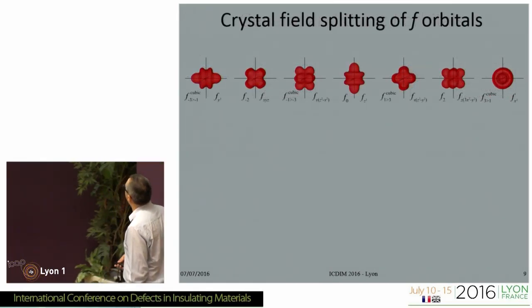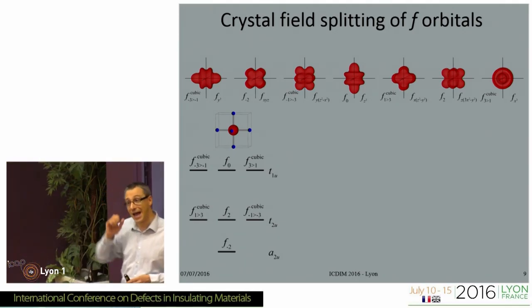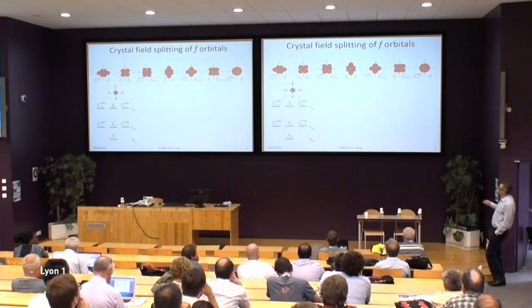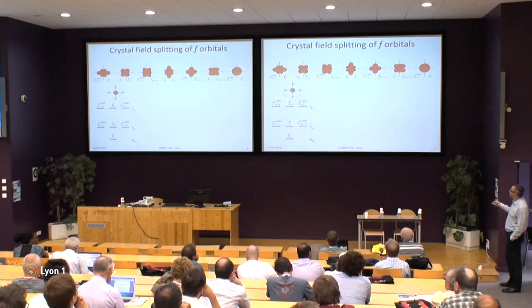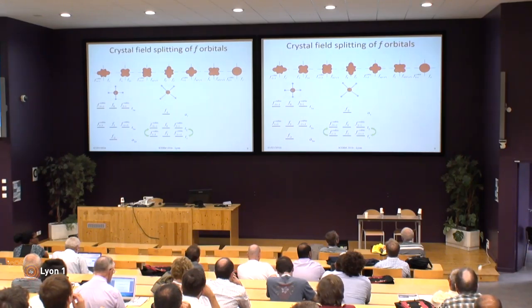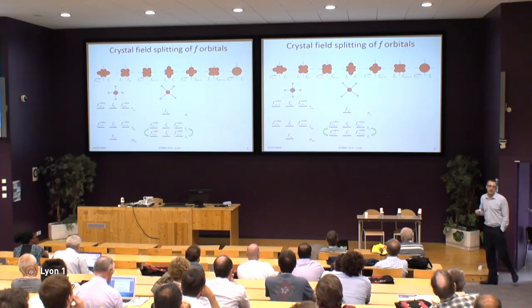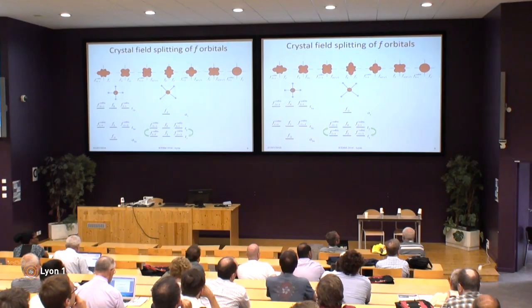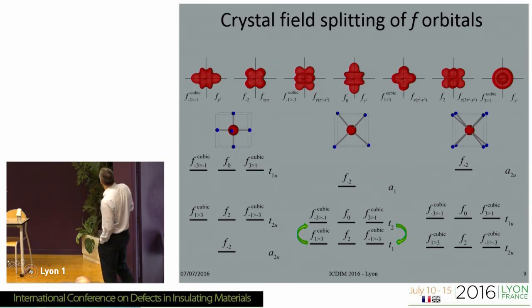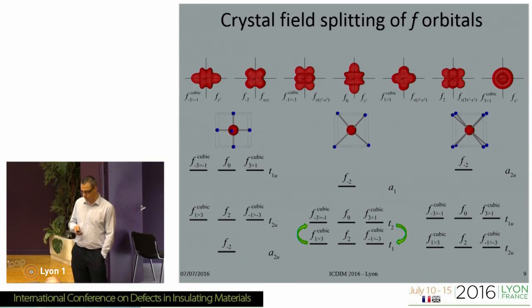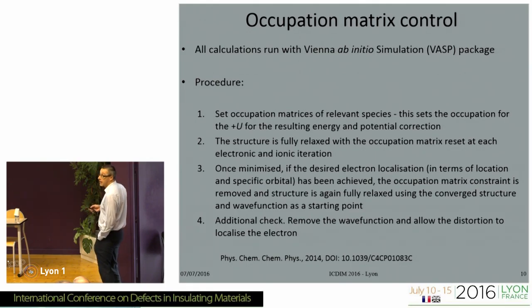There are seven F-orbitals, and the crystal field effects on these from the lattice are quite small. That's very true, but there is an ordering: in octahedral symmetry you'd have a singlet A and two triplets. If you go to a tetrahedral system, you invert that, and this splitting is so small that the nature of the bonding can change the order. In the full cubic case, the field is slightly stronger and you tend to get the T2 below the T1. I mention this because I'm going to show it within the calculation in a moment.